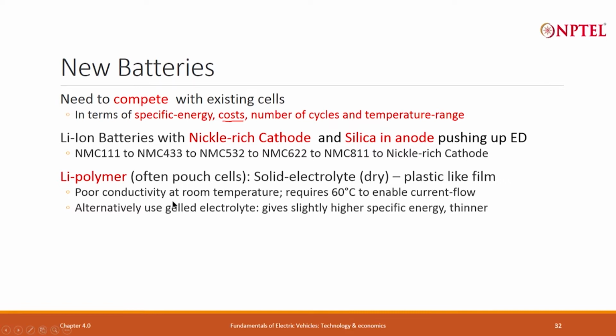The problem is, at room temperature it has a poor conductivity, you have to heat it to 60 degrees centigrade. That is not very desirable, but in India anyway the temperature is higher. If it is 10 degrees centigrade, heating to 60 makes a huge difference, but in India you may be able to use it a little, we keep on looking at it. There is also another thing which uses gelled electrolyte instead of the liquid electrolyte or the powder, plastic film like electrolyte. Gel gives you slightly higher specific energy density and makes the battery thinner. So, you will see lithium polymer coming in once in a while, you will not even know, it is still a lithium ion battery.